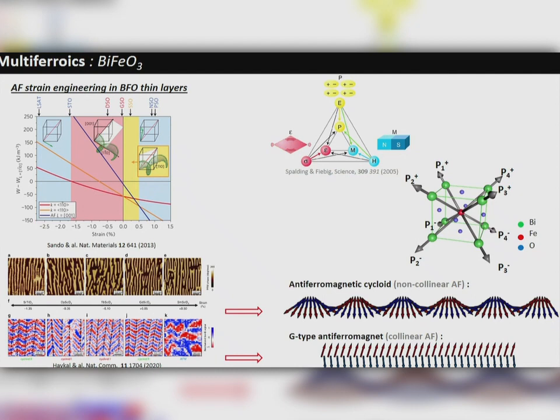For example, here you can see, again, you have the ferroelectricity, and here you can see some kind of cycloid. So you have the normal kind of cycloid, what we call the type 1, but we can also have another kind of cycloid, the type 2. I will not go into the detail of this because it's not the goal of my talk, but in some cases, you can destabilize the cycloid into a G-type antiferromagnet. So that means that by playing with strain engineering, you can really have a very nice zoology of different kinds of antiferromagnetic order that you can control.